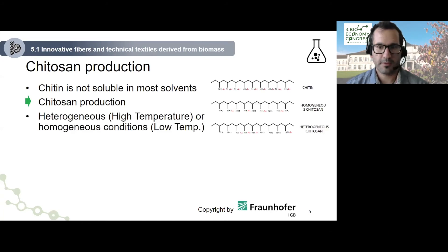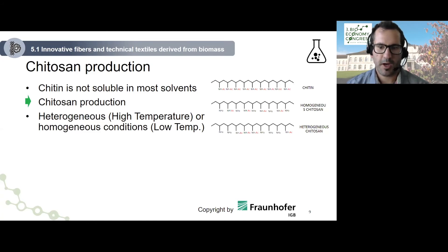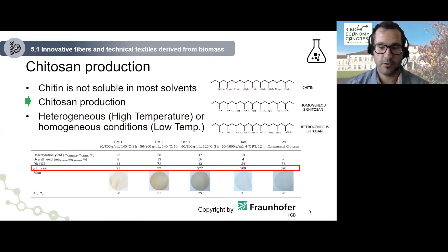One process applies high temperatures, called heterogeneous deacetylation, and the other applies homogeneous conditions — meaning low temperatures — for deacetylation. The difference results in different patterns of residual acetyl groups: homogeneously distributed when applying low temperatures, and heterogeneously ordered via hydrogen bridges at high temperatures. The table here covers various values characterizing the reaction and product, such as yield, deacetylation degree, and viscosity. The viscosity values cover a broad range resulting from different solid-liquid ratios or incubation times, meaning that chitosan properties can be fine-tuned by reaction conditions.